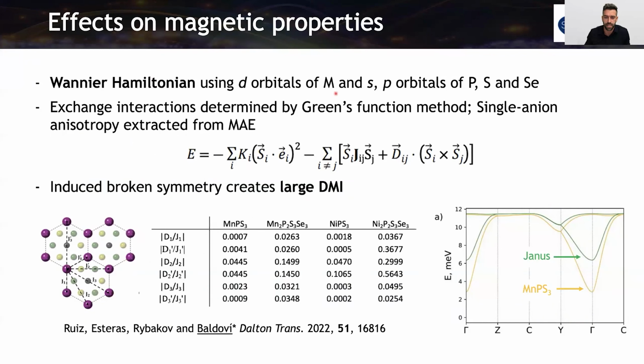In this case, we need the orbitals of the metals and the S and P orbitals of sulfur, phosphorus, and selenium. And we calculate the exchange interactions. And the most impressive thing here, which comes from these broken symmetries, is a drastic enhancement of the DMI. And this is reflected here. So these are the relation between the D and the J, the isotropic exchange interactions. And this is reflected especially in the magnon gap.